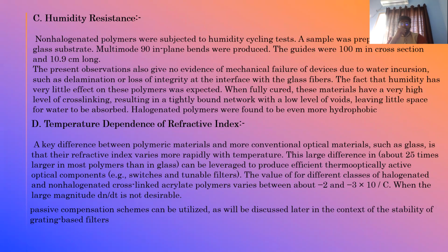The present observation also gives no evidence of mechanical failure of devices due to water incursion, such as delamination or loss of integrity at the interface with the glass fibers. The fact that humidity has very little effect on these polymers was expected. When fully cured, these materials have a very high level of cross-linking, resulting in a tightly bonded network with a low level of voids, leaving little space for water to be absorbed. Halogenated polymers were found to be even more hydrophobic.